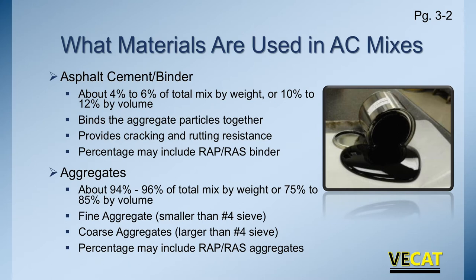What are the materials that we use in Virginia? In our mixes it's asphalt cement — it's the binder, the glue that holds those rocks together. It's about four to six percent of the total mix. In some mixes like an open graded drainage layer, we specify around four percent minimum. In things like our SMAs, it might be six or seven percent. It's about four to six percent of the total mix by weight, about ten to twelve percent of the volume. It binds everything, provides cracking and rutting resistance, and some of this binder comes from recycled asphalt pavement or, rarely, recycled asphalt shingles. RAP is a big component in much of the state, and most of our RAPs contain five or six percent binder that helps with the new mix.